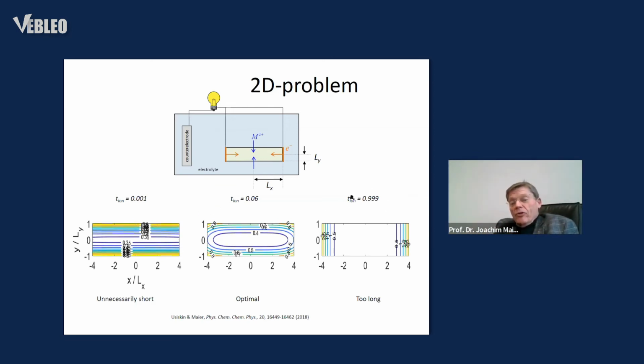But on the other hand, if your material is a good ion conductor, then diffusion starts from the sides. And this is very bad because it takes a long time. So obviously, this is then not a good morphology. In fact, you can show that this kind of anisotropy and this kind of oblong shape is best for ion motion.